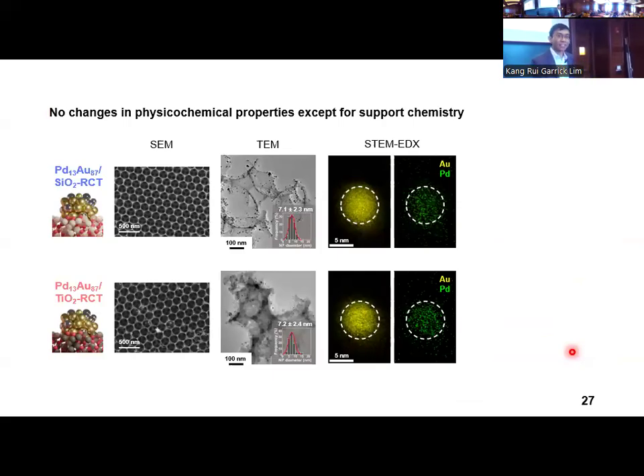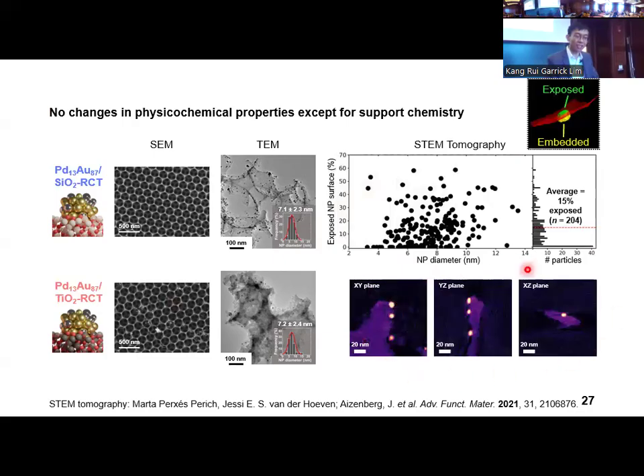For a fair comparison between the catalysts, we had to first ensure that the catalysts were similar apart from the support chemistry. Indeed, we observed no differences between the RCT catalysts in terms of their macroscopic structure, nanoparticle size distribution, nanoparticle elemental composition and distribution. Partial nanoparticle embedding in the RCT catalyst was visualized, then quantified by electron tomography. On average, about 85% of the nanoparticle surface was embedded into the support, leaving about 15% of the nanoparticle surface area exposed to the reactants. These largely compatible physical and chemical properties between the catalysts thus facilitated a fair comparison of their catalytic performances.